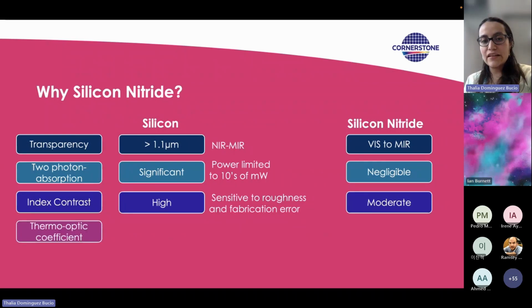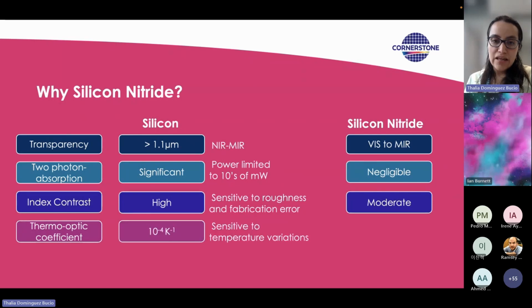The other characteristic that silicon has is that it has a relatively high thermo-optic coefficient. This is on the order of 10 to the minus 4 per kelvin, which means that you can exploit thermal processes to tune devices. It's very useful when you want to do a thermal modulator or a switch. But if you have an application in which you're using, for example, a high quality ring resonator that is very sensitive to temperature variations, you may not want silicon, because any temperature fluctuation in the room where you are will change the response that you're perceiving from your device.